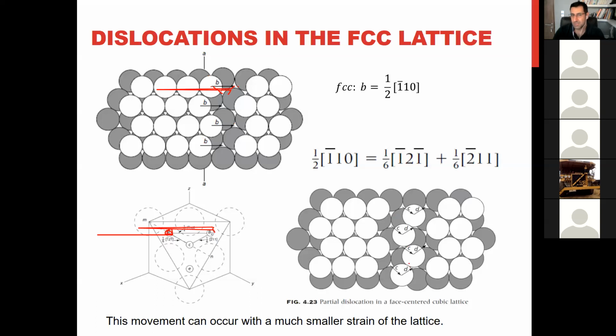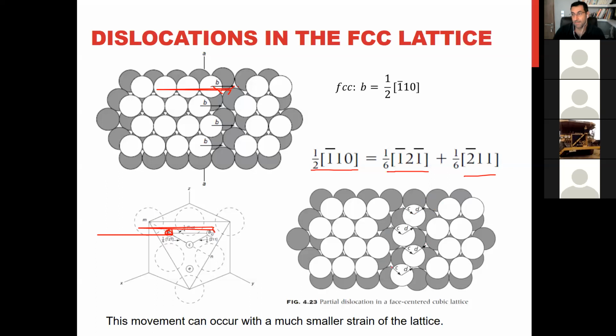But when you make such a situation, it means the dislocation movement is not completed. It's a partial dislocation. It means this dislocation is decomposed into two partial dislocations. This is one, and this is another. These are the Burgers vectors of these partial dislocations. So the decomposition of one dislocation into two partial dislocations helps the deformation in FCC crystals like this. Right? It's clear.